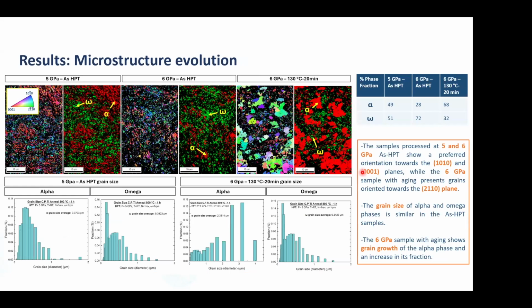These studies were carried out in Japan, and we investigated the fraction and the orientation of the omega and alpha phases, especially at 5 and 6 gigapascals, and also after aging. For 5 and 6, we know that the fraction after 5 gigapascals is something like 50-50. But at 6 gigapascals, the fraction of omega phase is roughly 70-30. And then when we age it, it's clear that the alpha phase statically recrystallizes in the microstructure, and we have a lower fraction of the omega phase. So this is an interesting way to control the mechanical properties of commercial purity titanium.